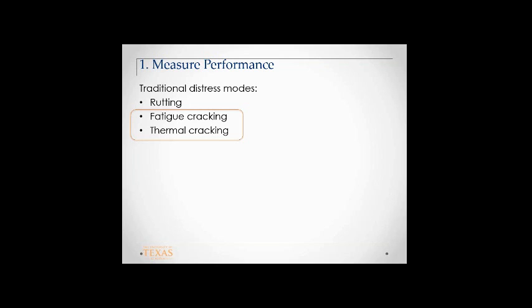And the reason why I'll pick on these two, and currently I'm picking on these two, is because if you think about the contribution of binder to these three components, binder is very much responsible for these two and is only partially responsible for rutting, because if you think of plastic deformation in an asphalt mixture, the aggregate structure, the aggregate skeleton has a lot to do with it. So binder has two, but it's an interplay between aggregate and binder.